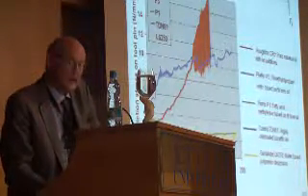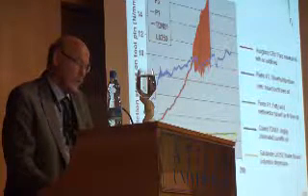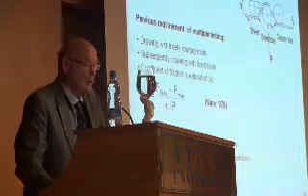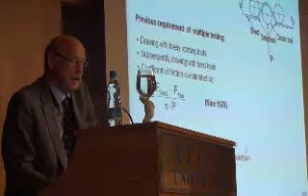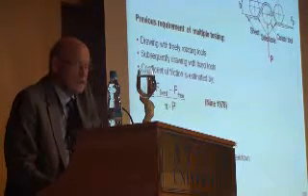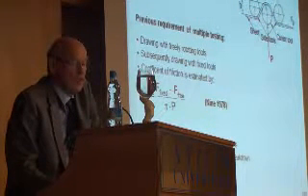Chlorinated paraffin oil works beautifully. That's the black one here. But we found other lubricants like the polymer coating, the yellow one, and the Pinifer, that is the fir tree oil based methyl ester, and they work just as good. The second test, drawbead test, is based on the same principle. Instead of doing the test twice here, we measure the friction directly by measuring the torque on the center roll.